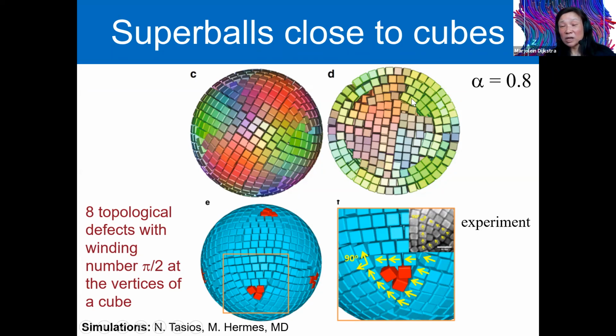There's a big block of simple cubic crystal in the middle, but also at the outside, the cubes really like to align along these spherical confinements. If you look at the outside, we find 8 of these topological defects with a winding number of pi/2, and it satisfies the Poincaré-Hopf theorem.